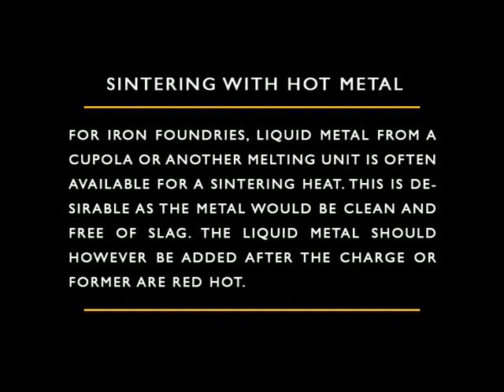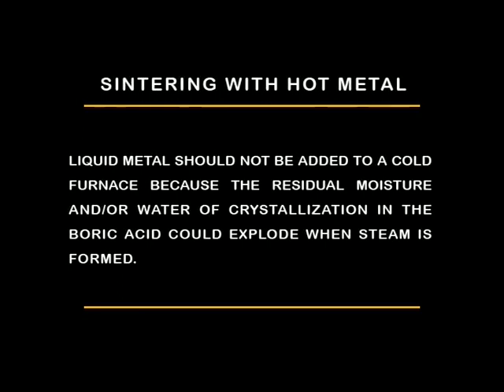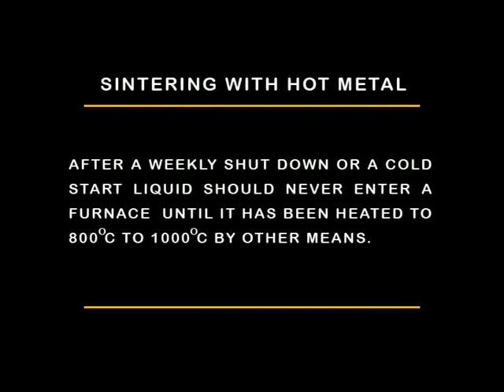The liquid metal should, however, be added after the charge or former are red hot. Liquid metal should not be added to a cold furnace because the residual moisture and/or water of crystallization in the boric acid could explode when the steam is formed.